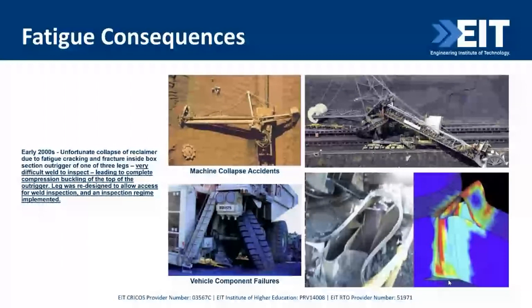The consequences, again, are obvious. The two on the left we needn't go through. The one on the right is an unfortunate collapse of a reclaimer, where there was an internal weld on all of the outrigger legs, which wasn't able to be visually inspected, and wasn't inspected, and it internally cracked, and the whole weld unzipped. Obviously the outrigger, with highly compressive loadings on that top flange right next to the hub, compressive buckled and completely unzipped. So that was very well proven in the simulations.